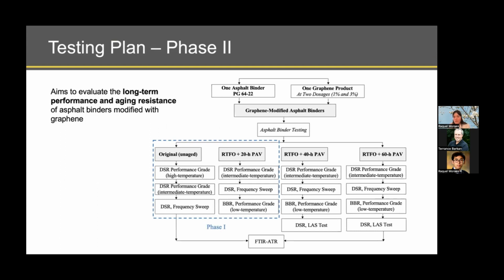And what we are able to see in the literature is that the dosage used for the graphene products were generally very low. Of course, that was product dependent and depends on the size of the graphene utilized and so forth. But what we saw is that the dosages were often very low because of the tendency of segregation of the graphene. So we got positive results in terms of seeing that we could go up to 3% for basic classification of binder.